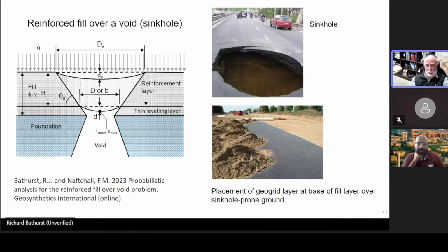So in fact, if the duration between the time the collapse has happened and the time you remediate is 100 hours, well, you'll be able to use a stiffer value in your calculations and therefore achieve a more effective solution. So our designs have as an input the amount of time that the reinforcement has to provide this support function.